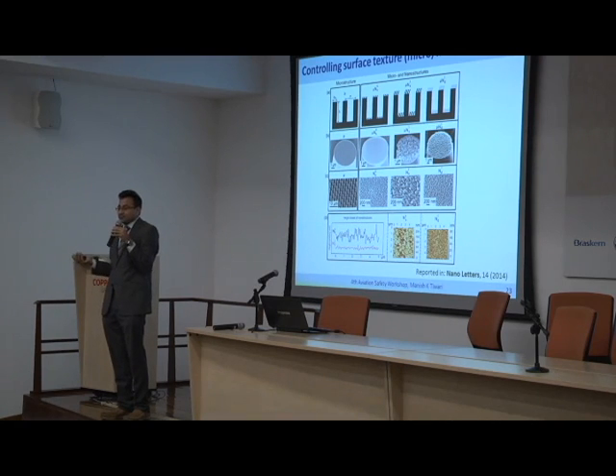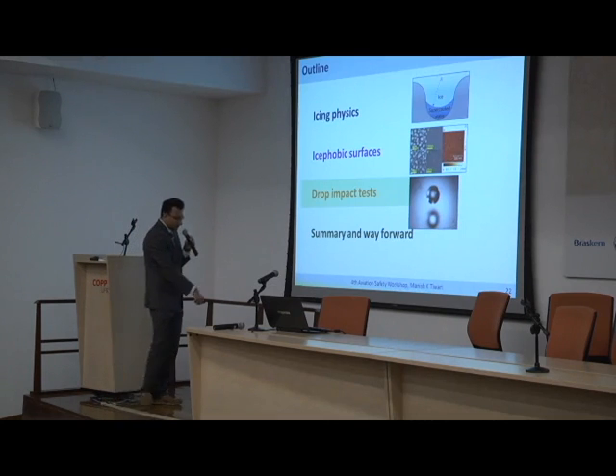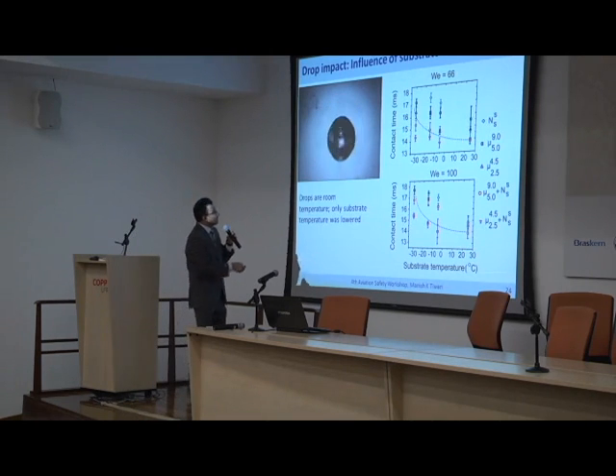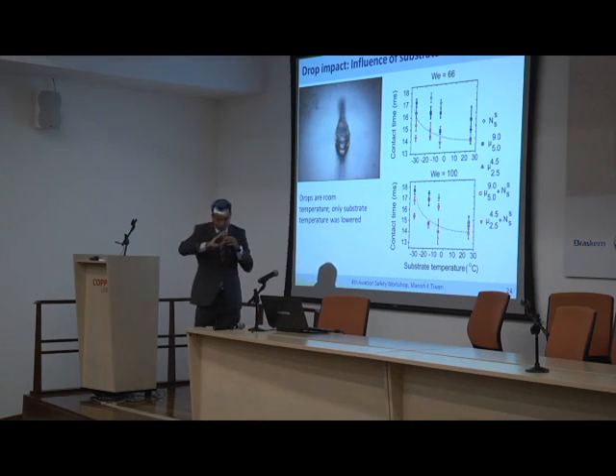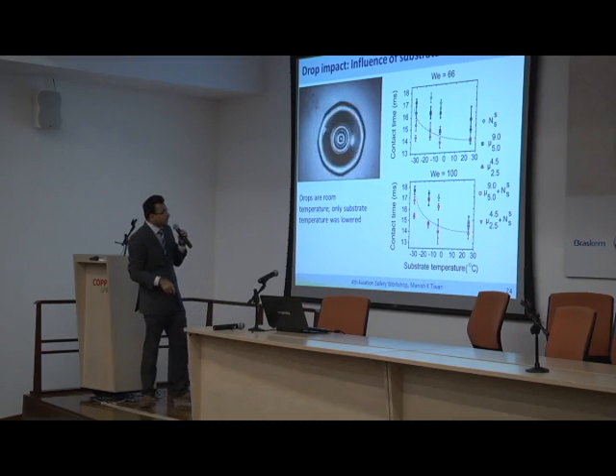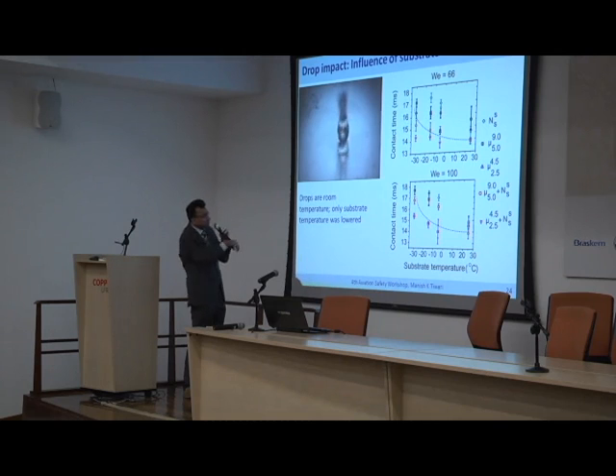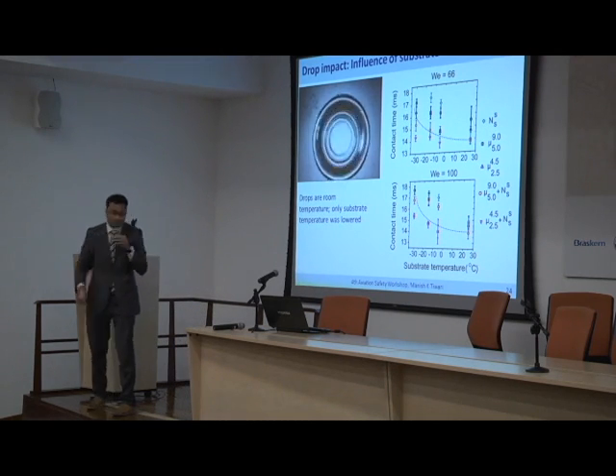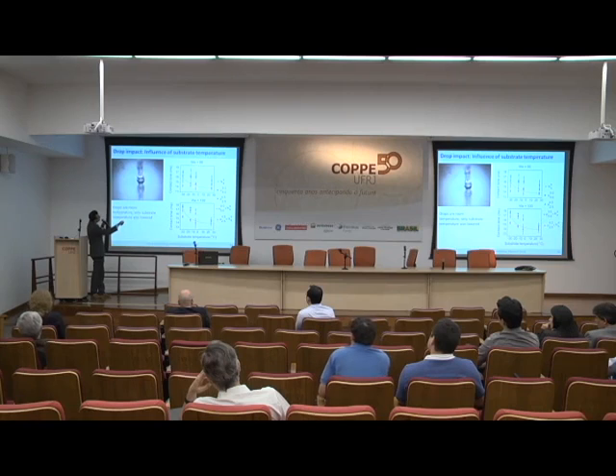If I want to use a superhydrophobic surface, I'd like to do what this guy was doing. It comes down and it takes off, right? So let's see if we can make use of that. So I want to make use of something like this. So the way we did this experiment is we designed a whole slew of surfaces, again, very regulated, and we tried to look at how the contact time of my droplet looks like. So how much time does my droplet spend on the surface during the impact event? And what we see is as we go down with the temperature, we have an increase in contact time.